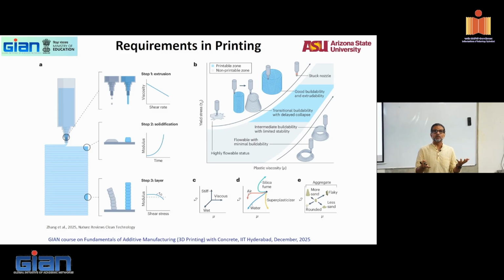But what is the downside of increasing yield stress? Which is you need more force to initiate flow. So yield stress increasing after I build the layer is great, but yield stress higher at the moment of extrusion is not very good. What you can do is make the mix in such a way that you can add admixtures, delay the open time, do all of that. But all of those gets very complicated, as you can see from this picture.